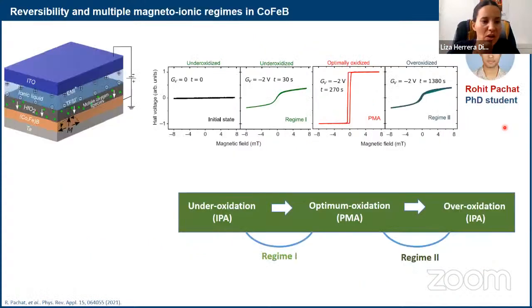So in this case we used a tantalum buffer layer. Everything is amorphous, and here we found something that I already showed you. We start with an under-oxidized state. If we keep applying, in this case, -2 volts, we keep pumping oxygen species into the system. We will go eventually towards an optimally oxidized state. But then, which is something I didn't show before, in the same system you can push it further and then over-oxidize it.